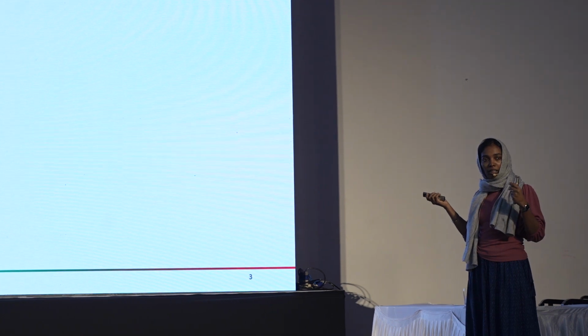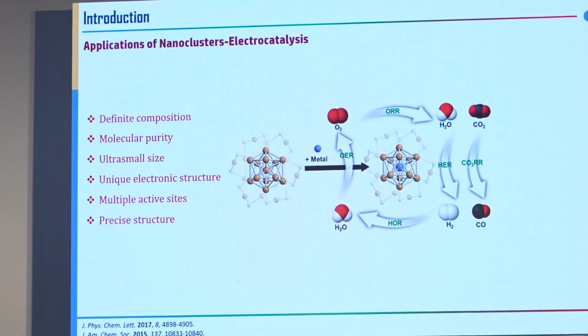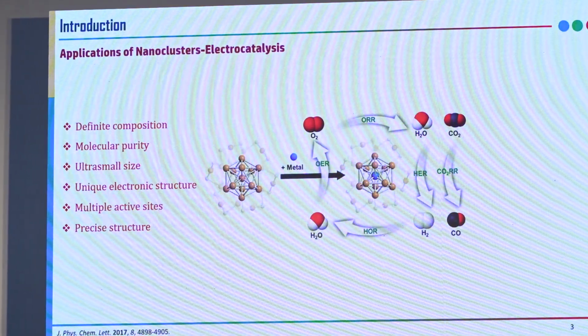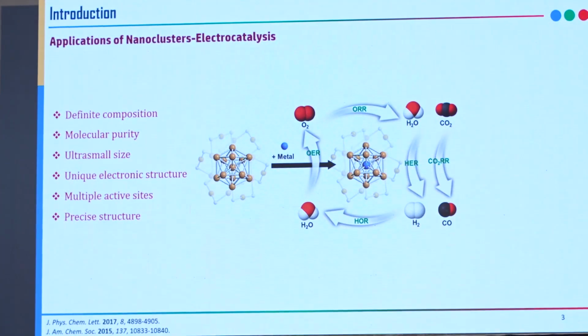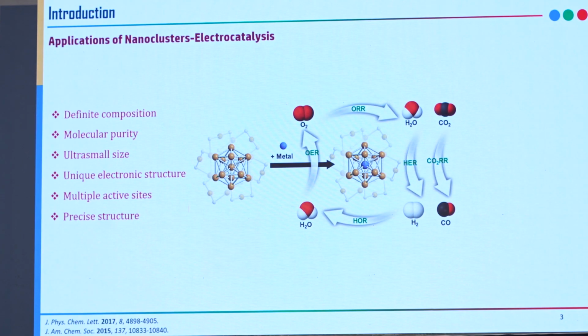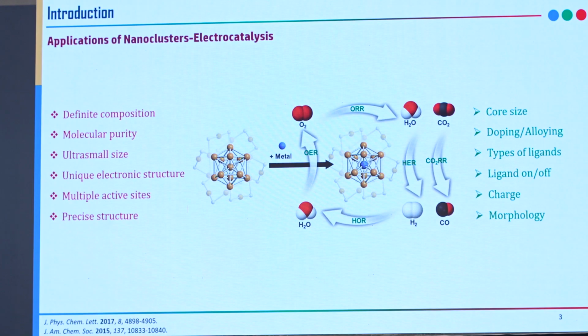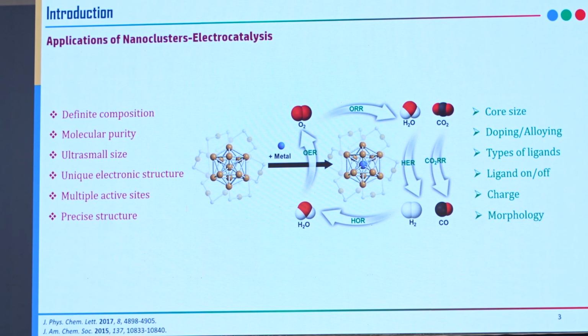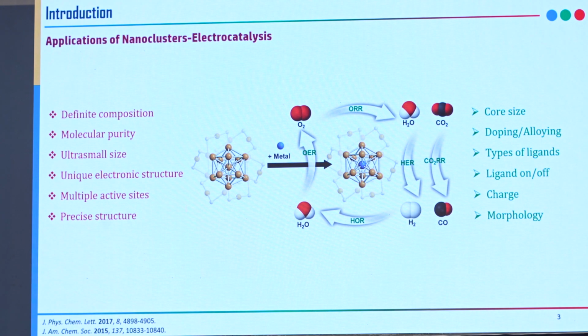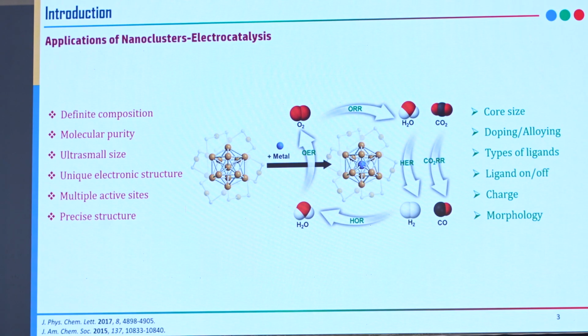Due to this quantum confinement effect, we can tune the energy gap between the atomically precise noble metal nanoclusters using different methods like doping and heterometal doping. So we can use these nanosystems for electrocatalysis due to this tunable quantum confinement effect, in different applications like OER, water splitting reactions, carbon dioxide reduction reactions, and so on. But the problem in the field of these nanoclusters as electrocatalysts is the presence of the ligand which passivates the metal core. So the exposure of the metal core is very low in electrocatalysis. So people are trying to do electrocatalysis using different methods depending on core size, doping and alloying.